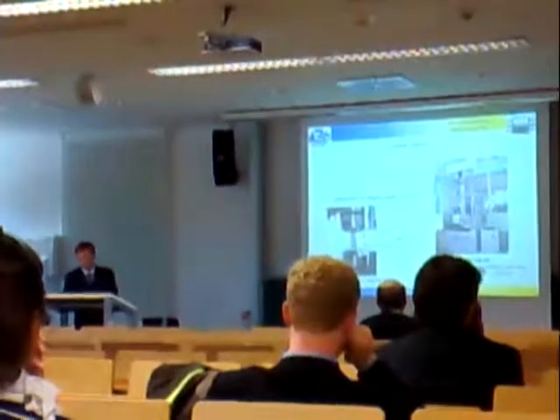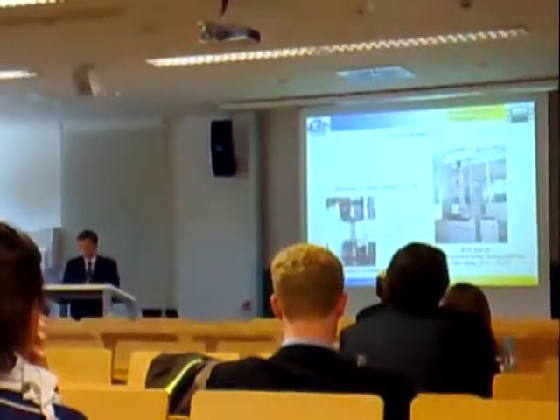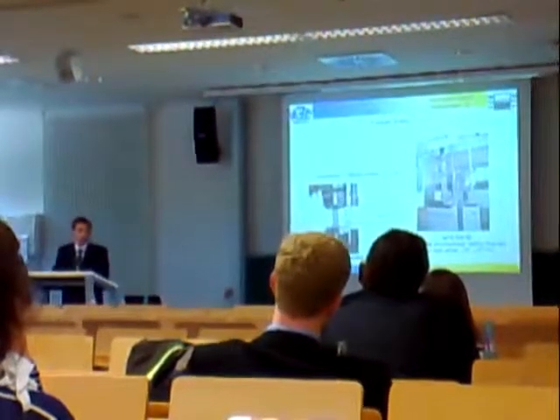Specimens for fatigue testing were manufactured out of separately welded plates with weld starting and ending on run-on and run-off tabs. Specimens' appearance and dimensions are shown in this video. Specimens were tested using a servo-hydraulic testing machine, MTS. Axial load was applied according to a sinusoidal load time function. The stress ratio was set to 0.1 and 0.4, and the oscillation frequency was 5 Hz. Specimens were tested until complete failure.